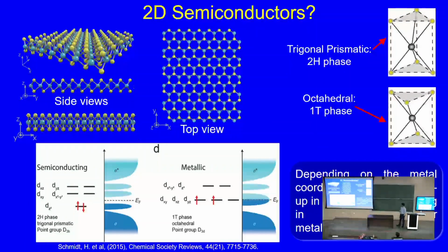Now if you talk about 2D semiconductors, for example TMDs, in this case you have a transition metal and chalcogens, right? And depending on the phase in which the transition metal and the chalcogens are arranged, they can be 2H phase or 1T phase, or trigonal prismatic phase or octahedral arrangement. Depending on this, you get different characteristics. So 2H phase is the most common phase which leads to a semiconducting property or semiconducting phase, and 1T phase is also possible, which basically results in a metallic state of the material, right?